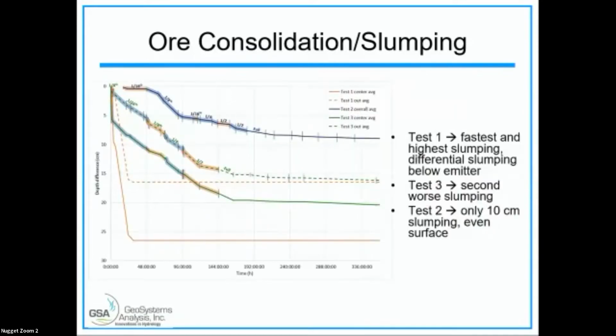Now this is looking at it again, time here and this is the collapse. Here we have the three different tests. This very first one shows the collapse with full irrigation. And wow, within 24 hours, it had completely collapsed. This is in the center, this is in the side. Now test number 2, which was the very slow ramp-up, there was no difference between the inside and the outside collapse. It collapsed very slowly, and we got down to about 10 centimeters, which is about a 5 to 6% settlement, which is probably ideal in a heap leach environment. And then the fast ramp-up test had an intermediate collapse, where this is on the edge and this is in the center. Next.